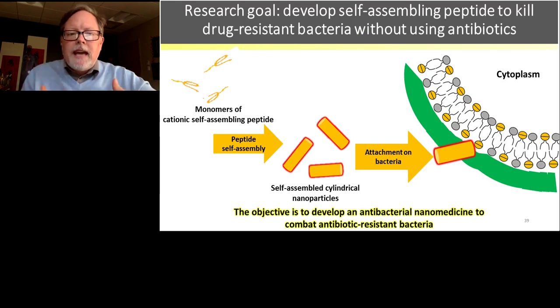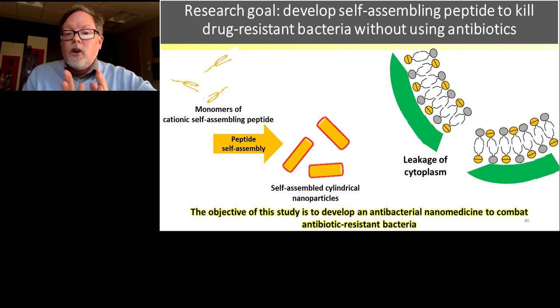So again, the picture of how this happens: we create monomers of these cationic self-assembled peptides. They self-assemble into cylindrical nanoparticles or rods. They first attach to the cell membrane, but then because of their charge, they go into the cell, creating a hole, creating this leakage of the cytoplasm, which results in their death. But please keep in mind, the same thing does not happen for mammalian cells because of the inability of these particles, these fibers, to get through a mammalian cell membrane.